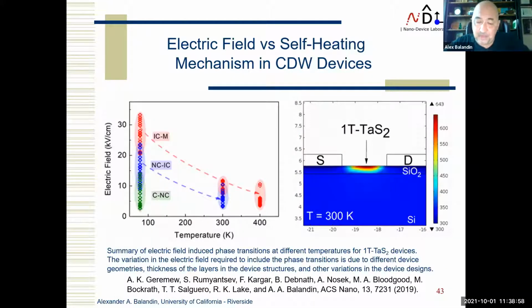What we also proved by using devices with different geometry is that the transition, in the classical design, when you have just a two-dimensional charge-density-wave material on a silicon oxide substrate, is still Joule heating induced. So it's not a pure electrical field effect, it's still Joule heating. We're only applying bias and current, even though the bias in our case is much smaller than in typical resistive switching devices, we still produce enough heat for the material to switch. So then the question we had: it still doesn't mean that you cannot achieve conditions where it will be a pure electrical switch.